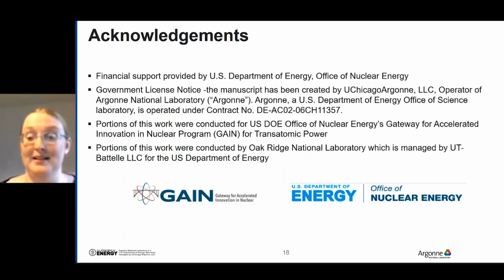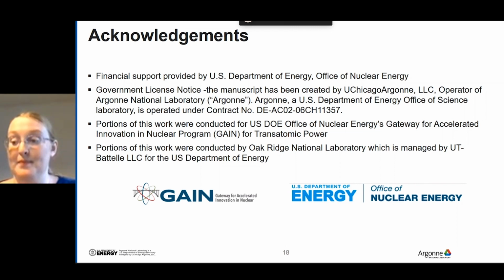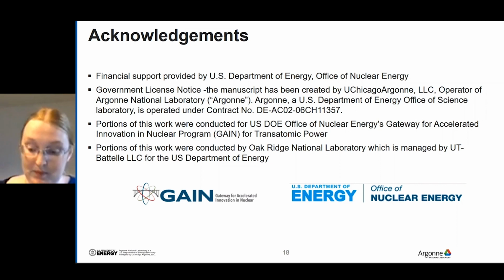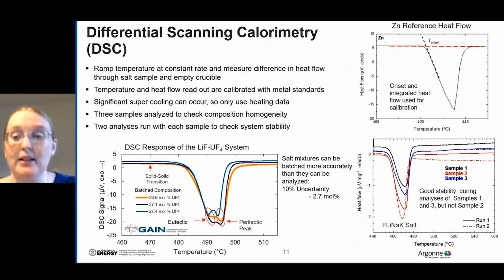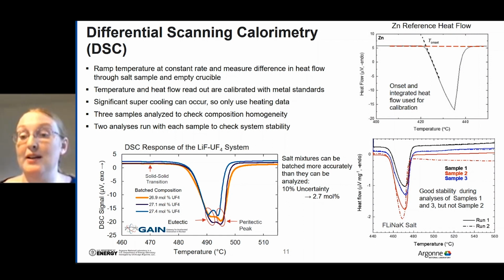Thanks, Melissa. So could you explain how sample 2 is unstable in slide 11? DSC is a very sensitive technique. So the reason for this instability, this difference between run 1 and run 2, could have been simply that the oxygen in the box changed. It could have been that someone was working a couple windows down from the device. It's really an environmental instability.